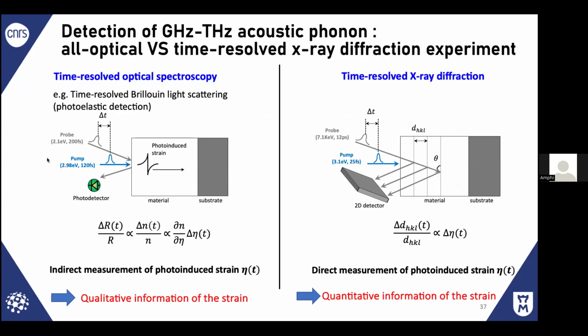Basically, there are two situations. If you still work with, let's say, optical pump-probe, phonons usually modulate the refractive index. This is the photoelastic effect, the so-called Brillouin, or the same thing if you have an optical phonon, you have the Raman. So motion, I mean atom vibration, modulates the dielectric constant. And if you modulate the dielectric constant, you can get the information through the optical parameters such as reflectivity or transmission.